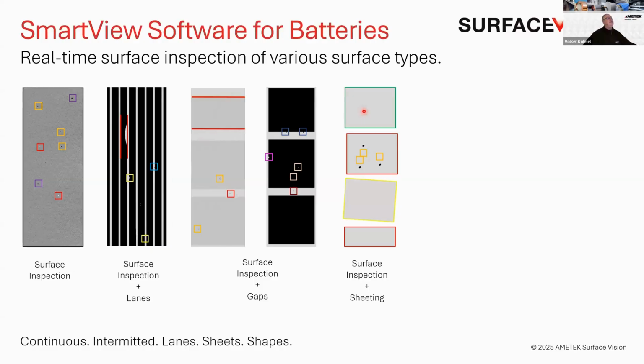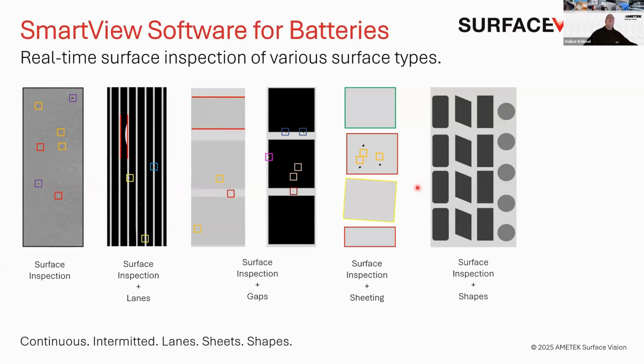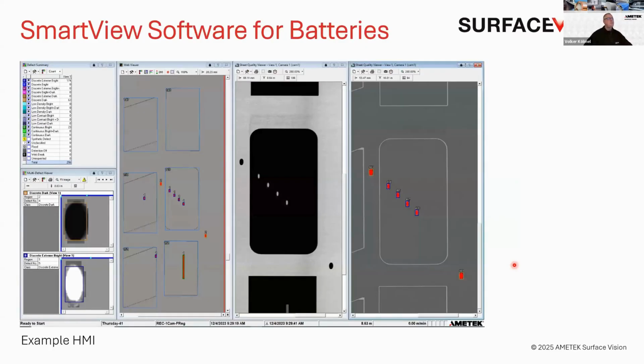And when you do the intermittent coating, then afterwards you also have to inspect sheets, like I've shown before on the blanking lines. And when it comes to the notching and the cutting of half cells or cells, we cannot only rely on square shapes. So we see cells, when they are notched or cut, they have a kind of radius on the edges or funny shapes. So we also had to develop a software which is capable to deal with all the different forms, which probably ends up in a final shape before it goes into the stack.